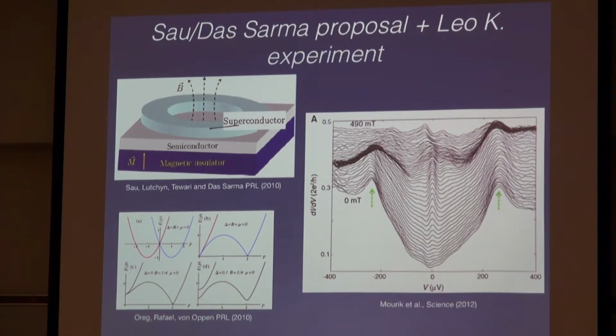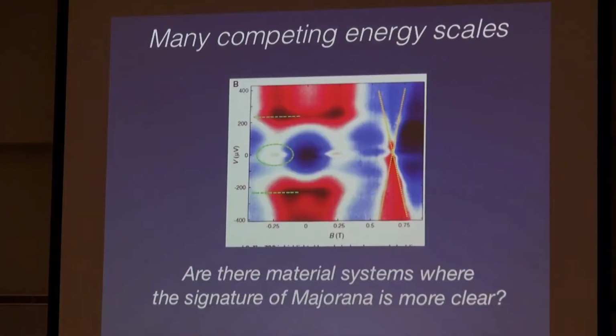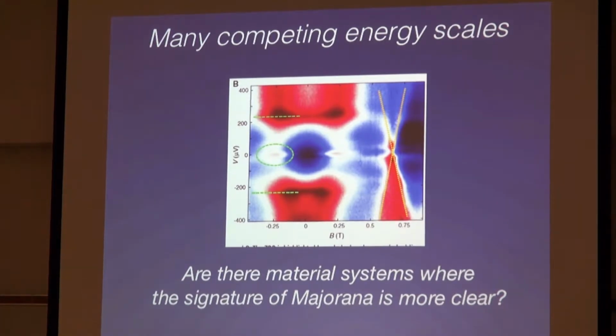And I think two years ago now, Leo Kouwenhoven's group did this, and they measured something that looks like this. There's a lot going on in this graph, but one of the benefits of this work is you can point to where the Majorana should be. This is as a function of magnetic field, this is the bias you apply to the device, and this is the conductance along the y-axis. At zero field, you don't see anything happening at zero bias, but as you apply the magnetic field, as you open up this gap at K = 0, you see the Majorana mode form. So this peak at zero bias is what you can point to as being Majorana. That was two years ago.